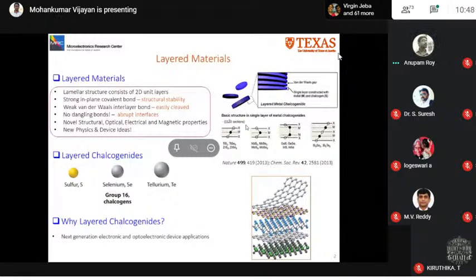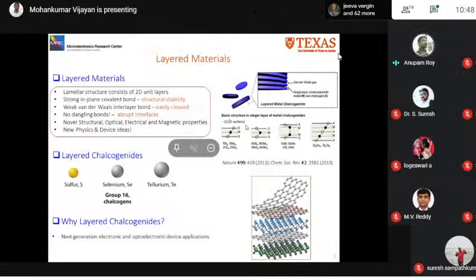So first, what are these layered materials and why are they very important? These are basically lamellar structures consisting of two-dimensional units, and in plane they are strongly bonded through covalent bonds that give these materials the required structural stability. Out of plane they are weakly bonded through van der Waals bonds, and that's why these materials can be easily cleaved. Usually the cleaved layer doesn't have any dangling bonds, so we can make multilayers with very sharp interfaces consisting of different types of layered materials, like metallic graphene, semiconducting transition metal dichalcogenides, and insulating hBN. Usually they are hexagonal in structure.